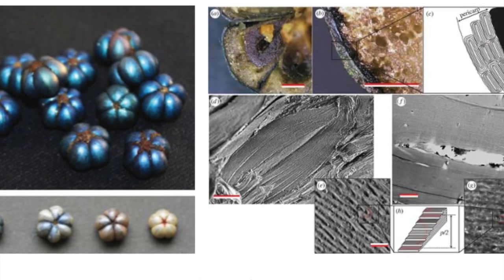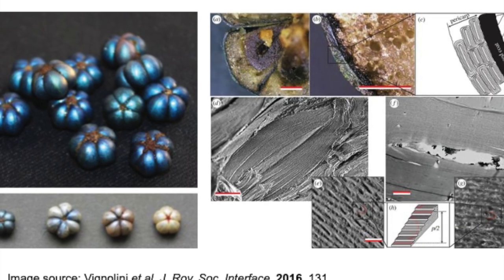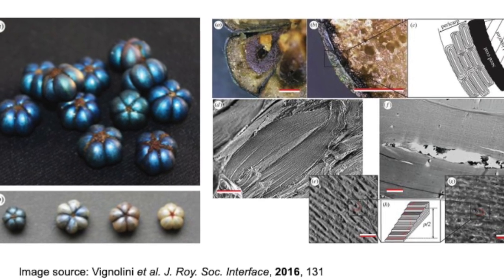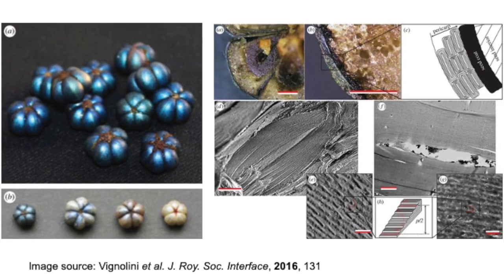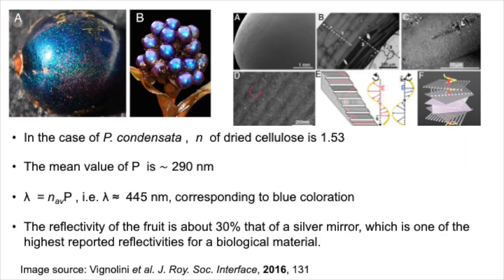The fruits of Margaritaria nobilis possess a helicoidal cell wall architecture that generates an intense blue-green coloration. In the related case of P. condensata, the refractive index of dried cellulose is approximately 1.53, and the mean value of the helicoidal pitch P is about 290 nanometers.